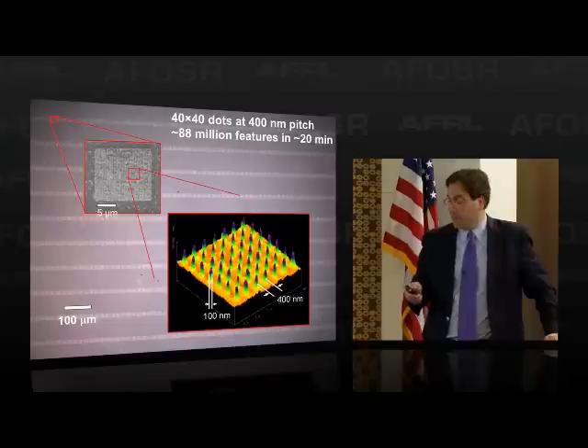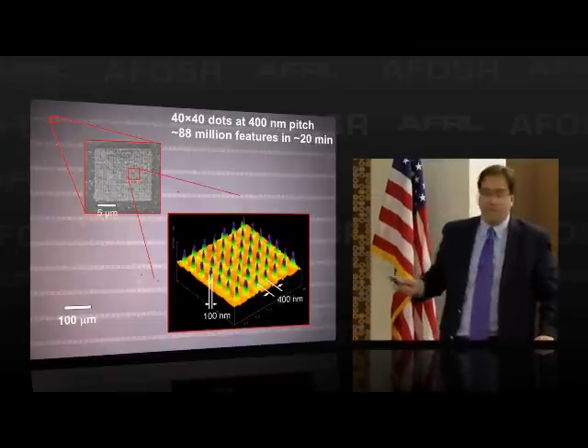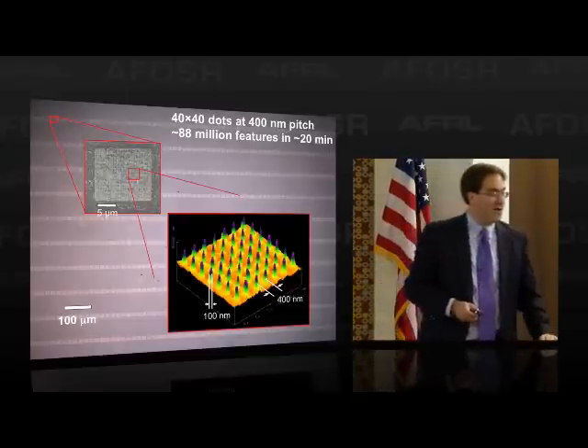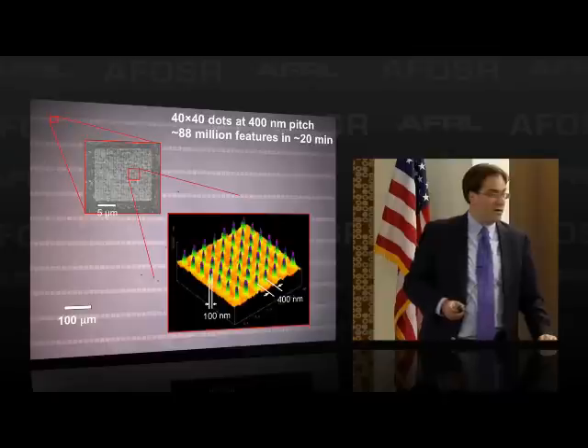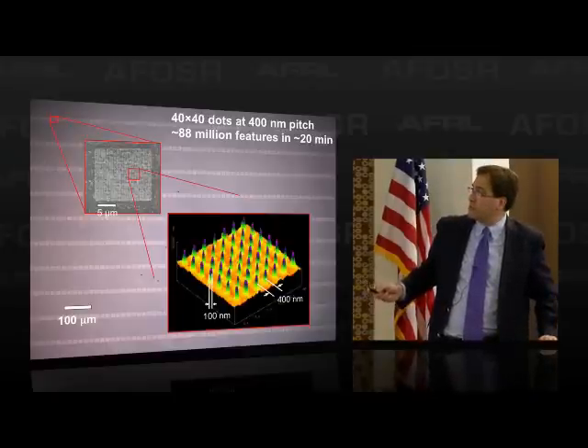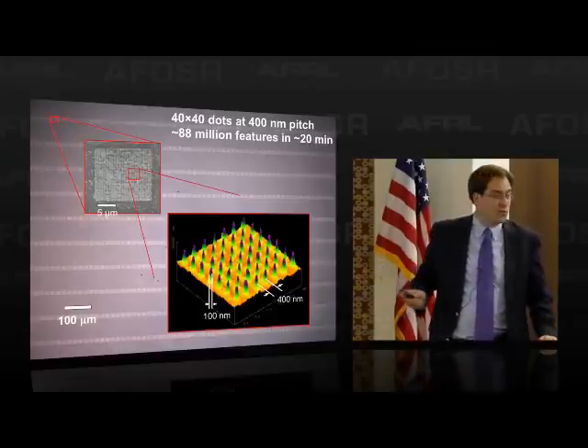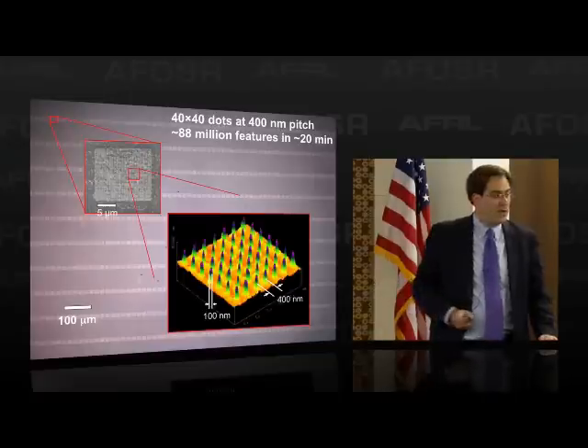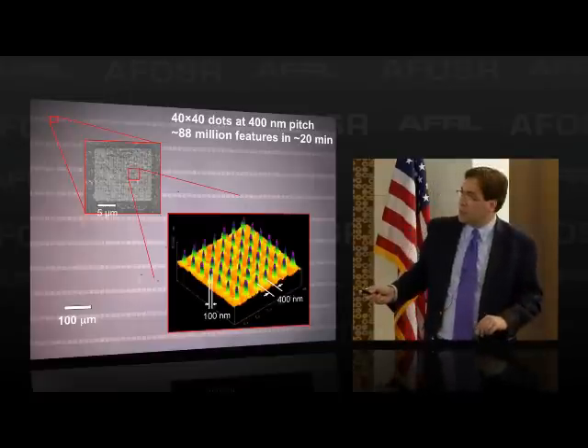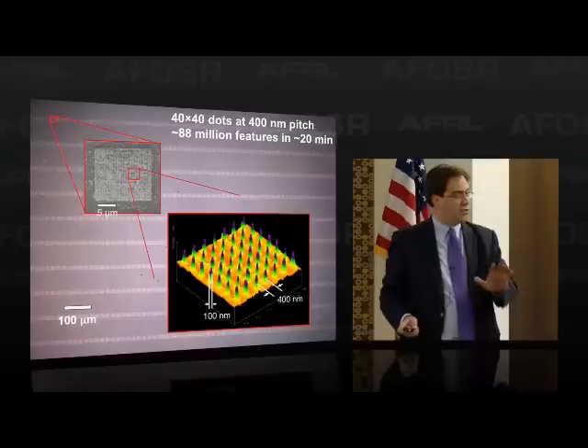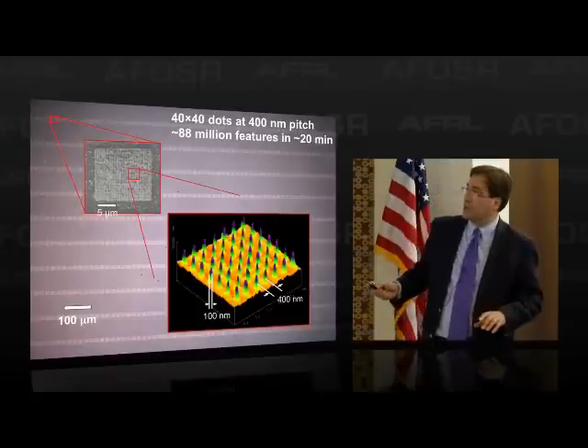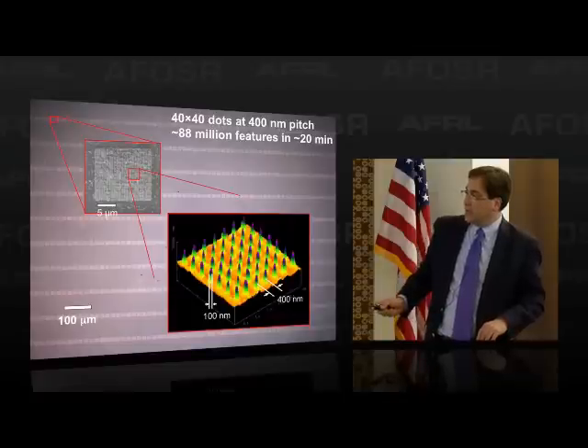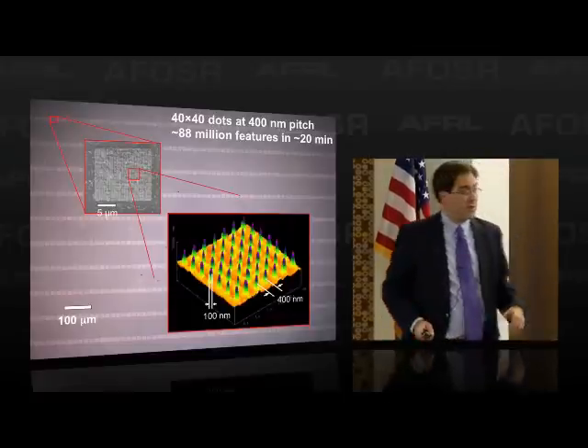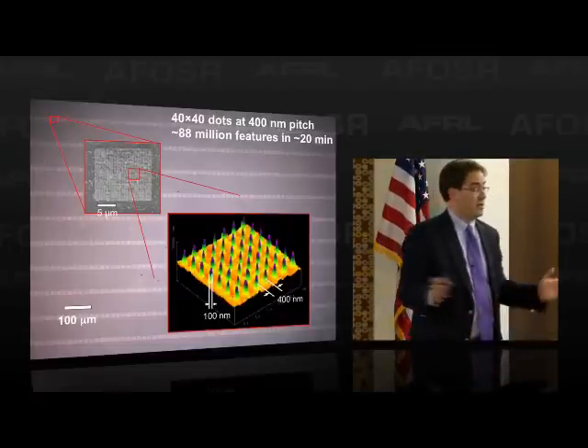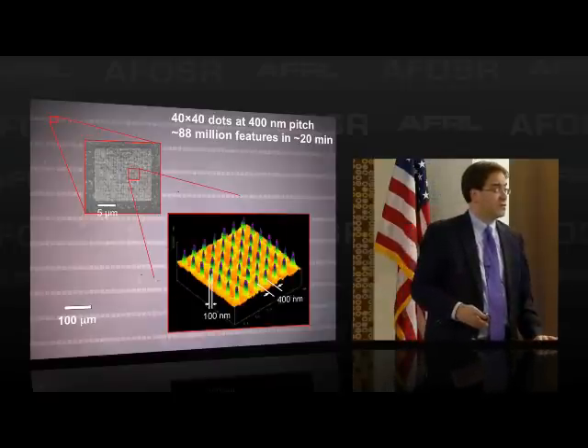And this was a big milestone. You have to, again, think of the challenge here. We now go from being able to print that 90 by 90 micron area to square centimeter areas. And here, these are all the tips printing, and we're making 88 million features in 20 minutes. Each of these were alkane thiols deposited on gold. And you're looking at the structure after we've etched it, so you can see the raised features and characterize them by things like electron microscopy. And you can see the uniformity is remarkable. I think it's about as good as you could possibly get with any type of tool, given the roughness of the surface that we're dealing with.